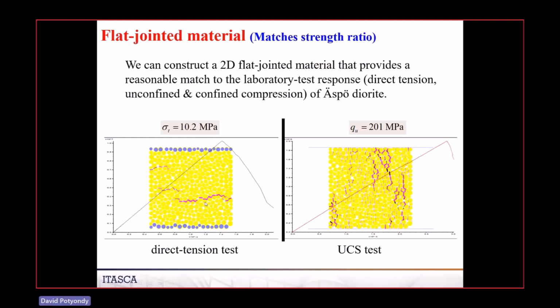And here's the tensile strength test. It loads up and then it fails. And you can see this is the damage that's occurred at this point in the test. So, okay, there's my tensile strength, 10 MPa. Then I take the same material and I squeeze it between platens to simulate a UCS test. And here you see you're going all the way up to 200 MPa. So there we've got this high ratio of compressive to tensile strength.